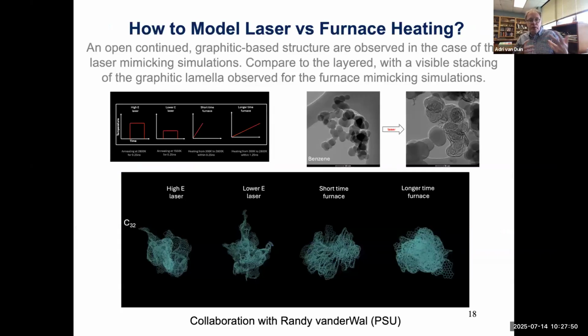So recently we started looking also at how temperature can affect it. There are different modes of temperature. We can have a relatively slow temperature, a long-term furnace where we very steadily heat up the material. We can do a short-term furnace where we have a more rapid ramp. But also what's very interesting is how this type of furnace-based growth differs from laser-based growth. In laser growth, we provide a sharp pulse. And we can do the sharp pulse at various levels. We can have a lower energy pulse, we can have a higher energy pulse.